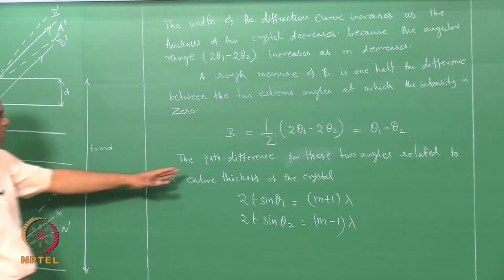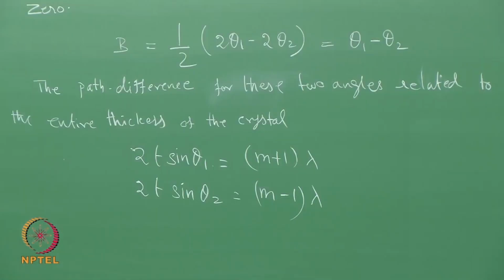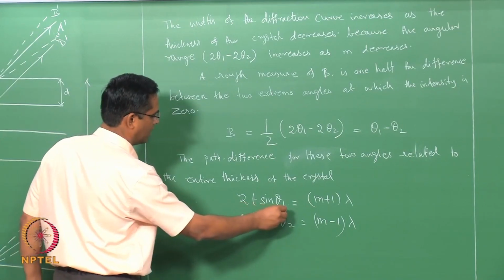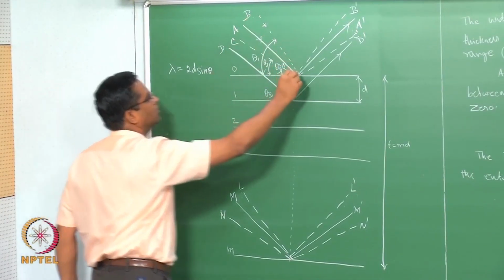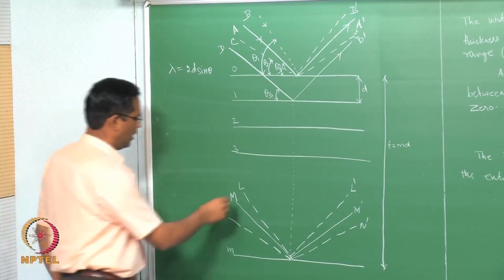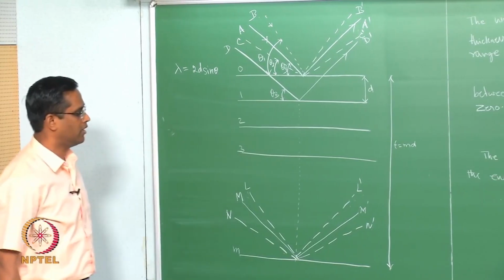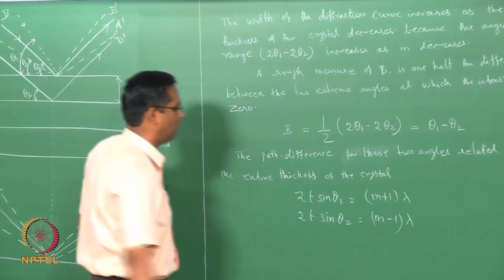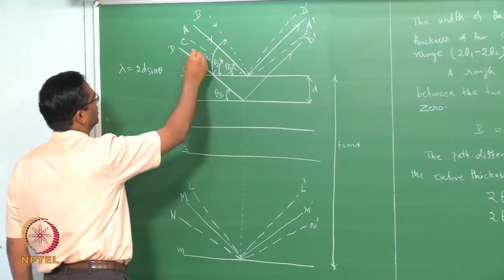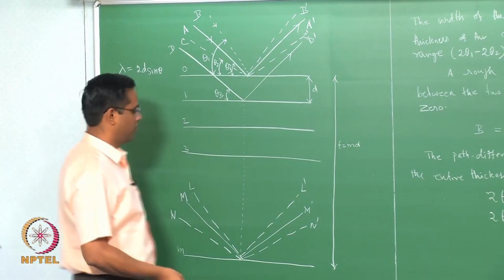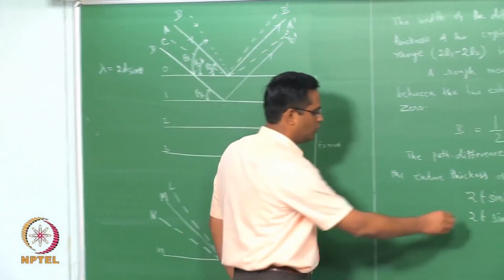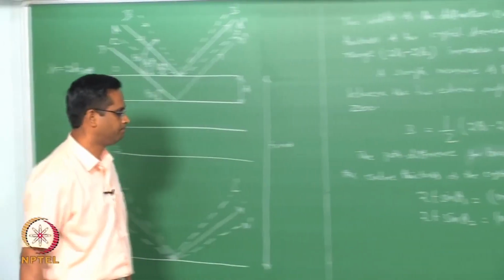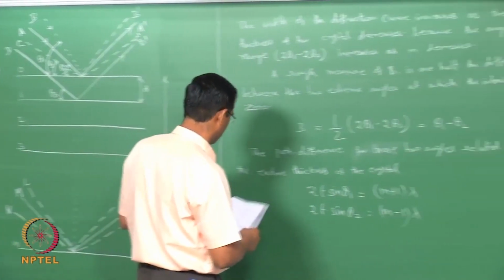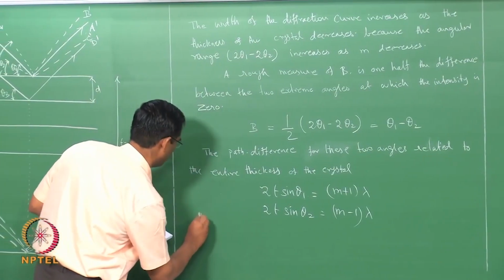So, the path difference for the two limiting angles related to the entire thickness of the crystal is 2t sin theta 1 equal to m plus 1 lambda. That means we are talking about this ray B prime with respect to L prime; they will differ in their path by m plus 1 lambda. The second ray, at an angle less than theta b, C prime, will have the path difference with respect to n prime 2t sin theta 2 equal to m minus 1 lambda. Now we will manipulate this by subtraction.